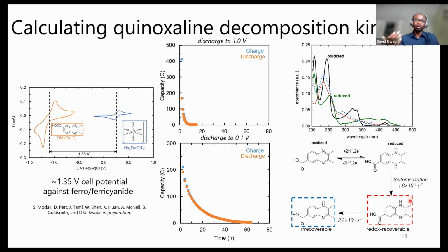That takes you from a molecule that's redox active to something that's either difficult to oxidize or completely redox inactive. And so if you can tune the pKa at this site so that the proton really wants to stay and doesn't want to move, then that's a big advantage towards suppressing tautomerization. So pKa engineering is one of them.